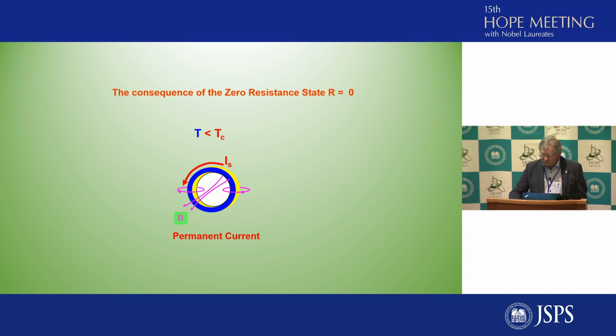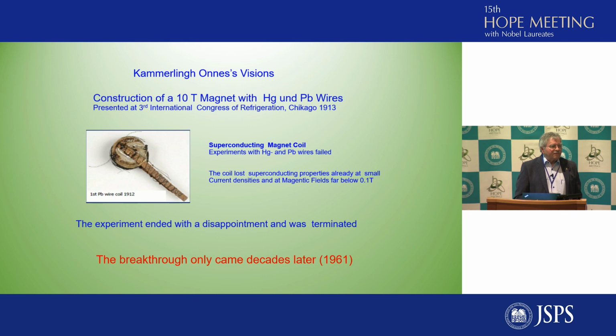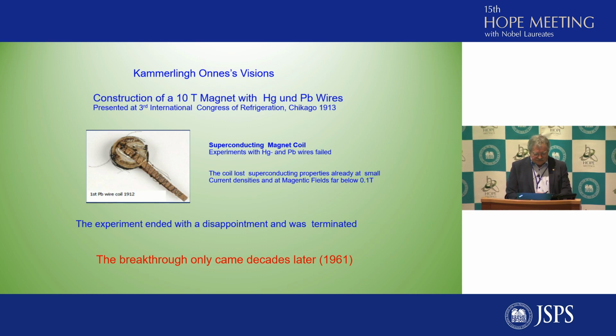So his first approach was to construct a very, very strong magnet, like 10 Tesla. This is more than a million times higher than the strength of the magnetic field of the Earth. But this failed drastically because the coil lost superconducting properties at very small current densities already, and at magnetic fields which were very, very low. So the experiment ended with a disappointment. It was terminated. The breakthrough, however, came only decades later, namely in 1961.